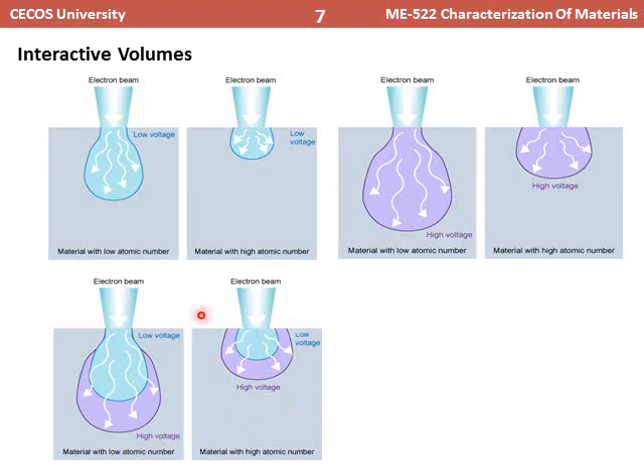So to sum up the discussion, we can easily visualize the impact of increasing accelerating voltage on the material or specimen, because by increasing the accelerating voltage, we are increasing the energy, and by this increase in energy the electron beam can penetrate to greater depth, both in the case of low atomic mass number and high atomic mass number. Definitely the penetration in the case of a low atomic mass number specimen will be much more as compared to the high atomic mass numbers.